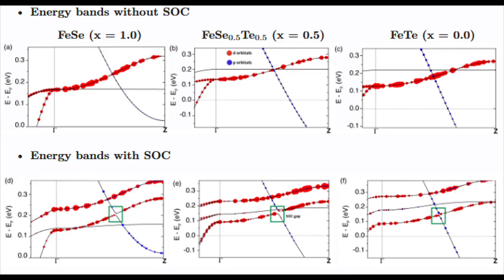8.93 milli electron volts for iron selenium, increasing to a maximum of 18.31 milli electron volts for iron selenium sub 0.5, tellurium sub 0.5, and decreasing to 10.73 milli electron volts for the compound iron tellurium. When X is greater or equal to 0.5, the main valence band contribution switches from d orbitals to p orbitals, resulting in a topological band inversion.